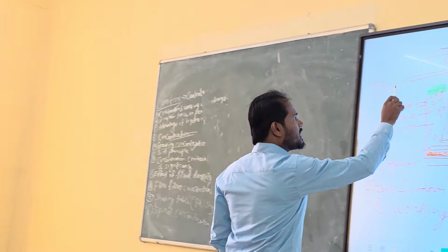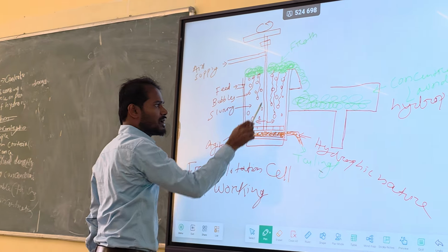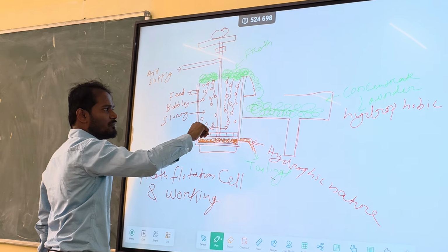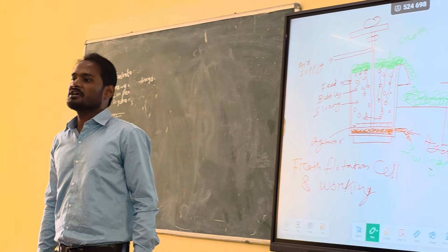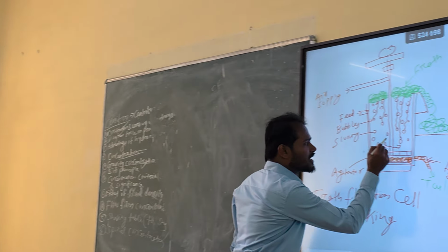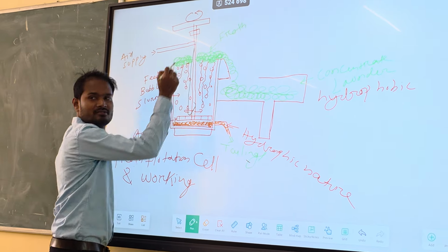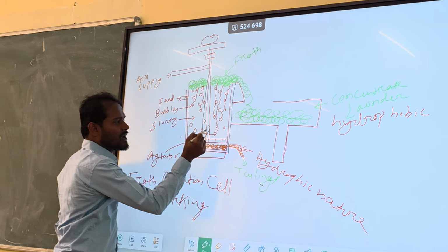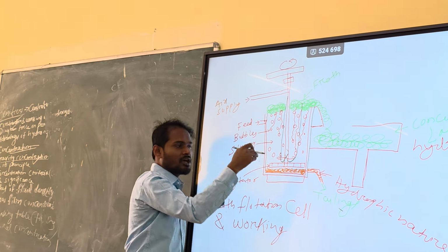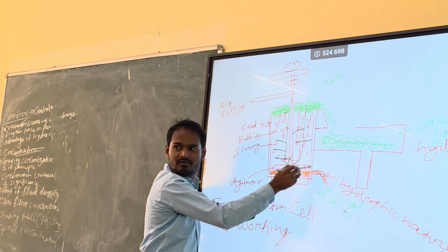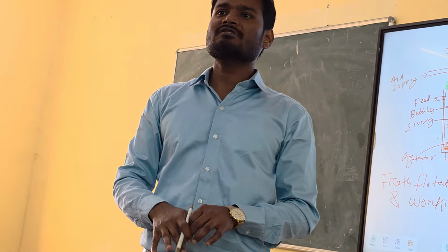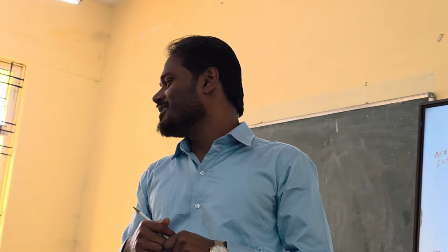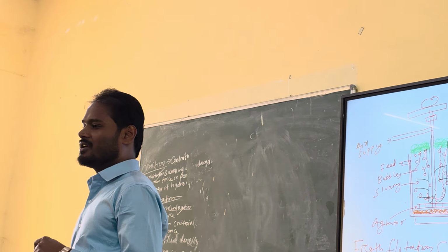And also you are supplying air, right? If you do agitation also, what will happen? Then this air will also get distributed throughout the slurry. Otherwise, air bubbles will come and may migrate like this, or like this. But if you do agitation, air will get sprayed everywhere. You have to collect the hydrophobic minerals from everywhere in the slurry, not from a particular point. So agitation is also required for that.